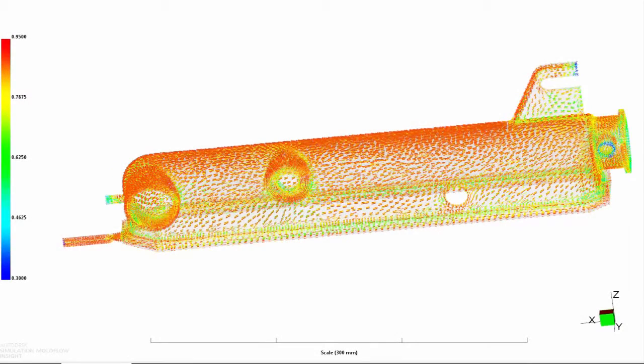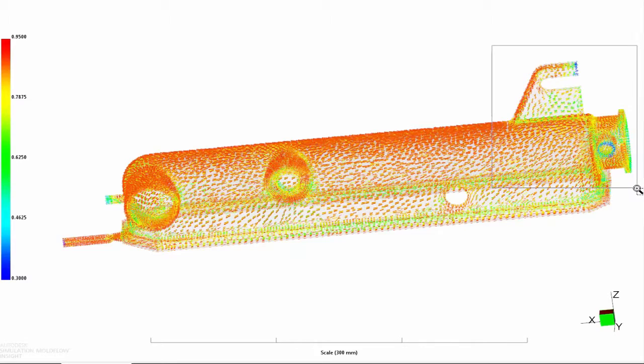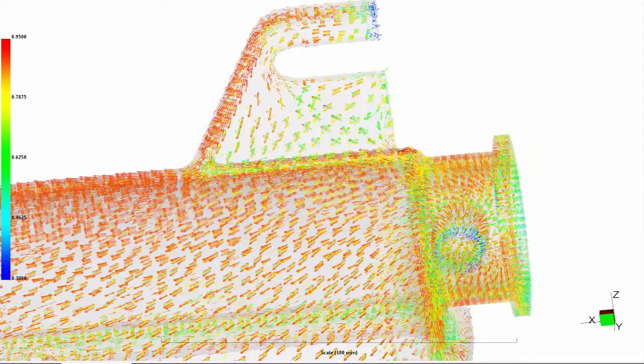Plastic polymer flowing through the cavity causes the fibers to align themselves depending on factors such as the direction of flow and the geometry of the cavity being filled. This variation in fiber orientation can cause great variations in mechanical properties throughout the part. Product warpage and premature failure of the part while in service may result.